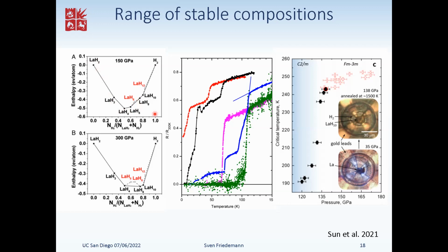It's still a question whether or not you form this, but you can see that there are many. So you could imagine that if you just start to react lanthanum with hydrogen, you could form LaH2, 3, 4, 5, 8, 10. And then there are also some which are not so far off. For instance, here LaH6 and LaH12 are only slightly above the convex hull. So with laser heating to 1,500 or 2,000 Kelvin, you could imagine that even those might be formed, trapped metastably. And indeed, that's what's observed.